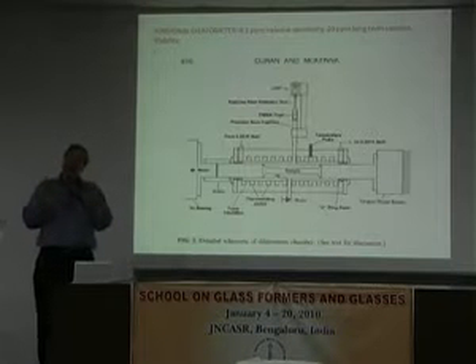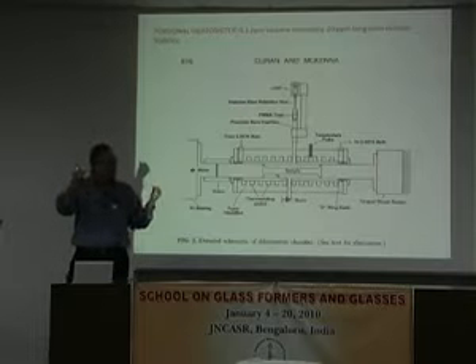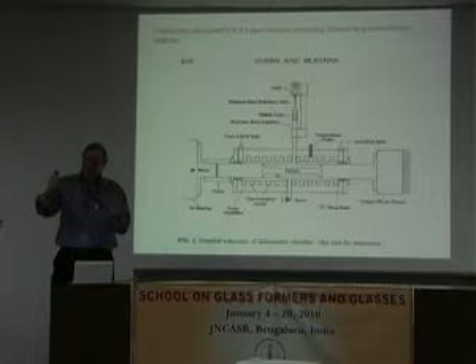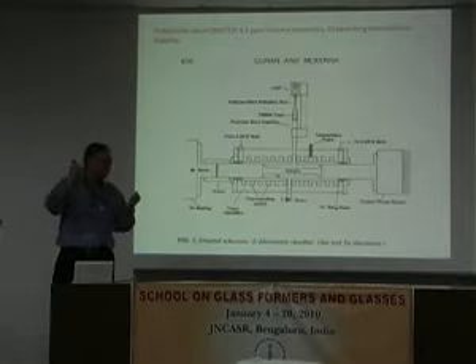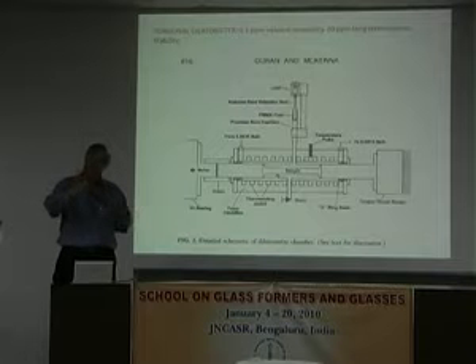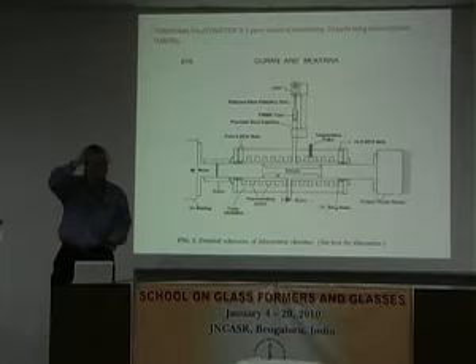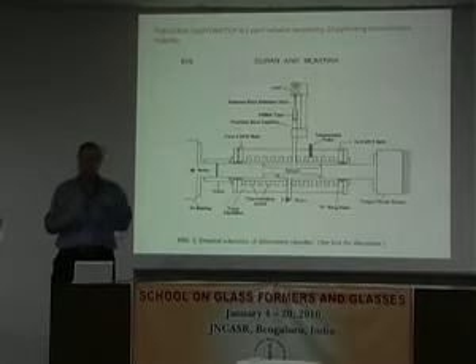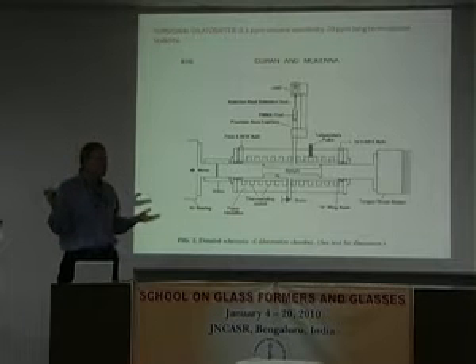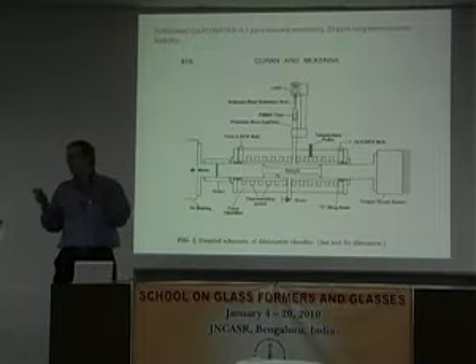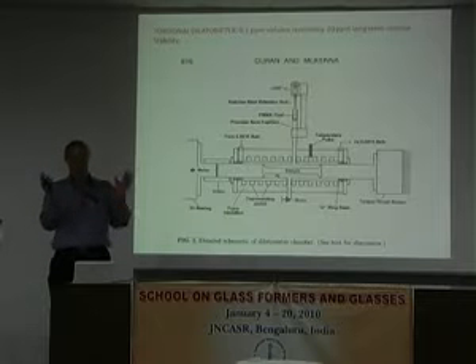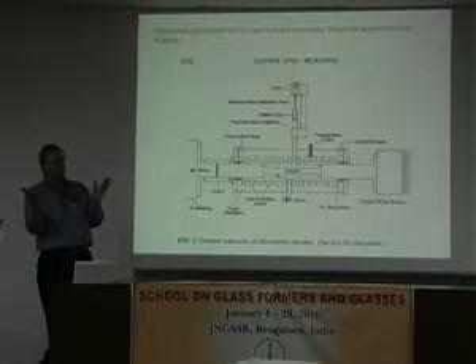Well, if I do a mechanical measurement in tension, the Poisson's effect in that tension, if the Poisson's ratio is 0.3, means that for a 3% strain, I'll get a 1% volume change. That'll be way too big to then try to do what I'm doing. In other words, you'd be trying to take a small difference between big numbers and then interpret it.